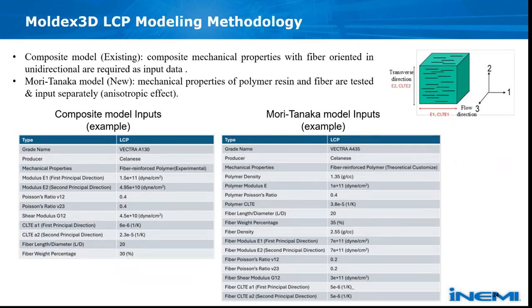Next. So to calculate the warpage of a fiber reinforced plastic product, generally the simulation tool will ask the user to input the mechanical properties of the plastic such as modulus and CTE under the condition in which all fibers are aligned in the same direction. Then the mechanical properties can be transferred to the condition with different fiber orientation probability for each mesh element. In this project, 2 methods to input the mechanical properties of fiber reinforced plastic are used in the validation. The first one is measuring. We can measure the mechanical properties of a composite sample and directly input the data.